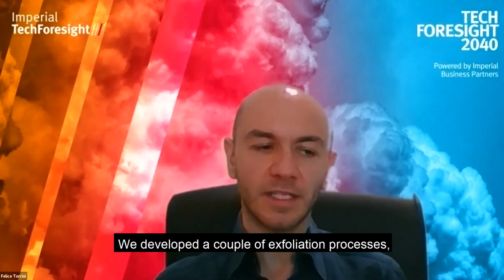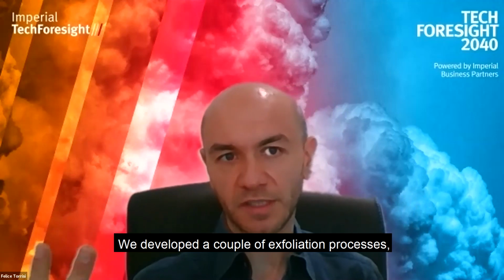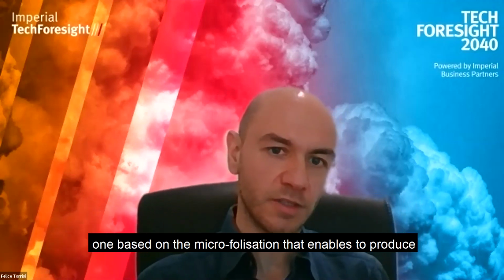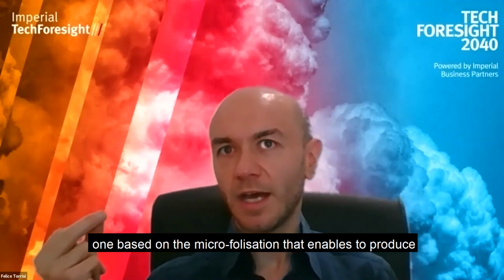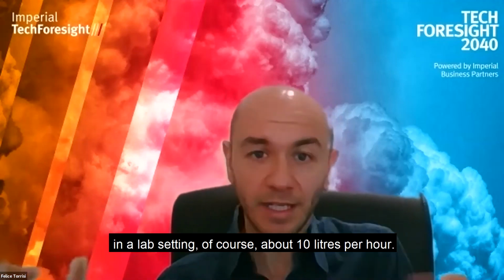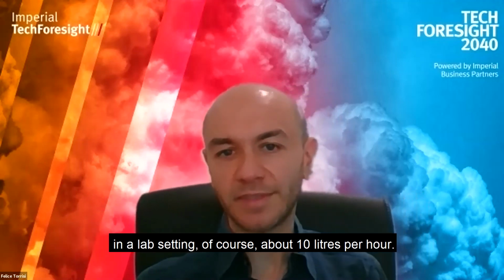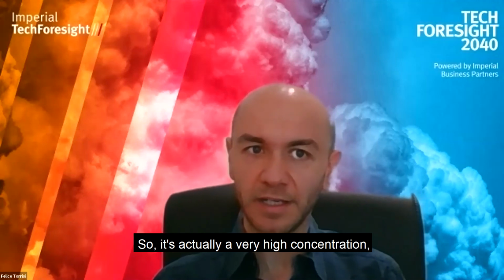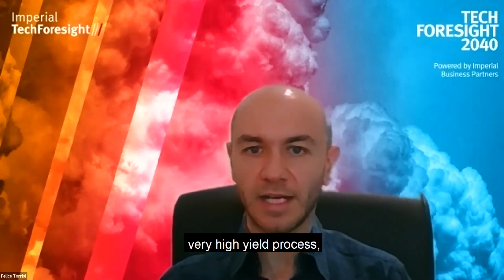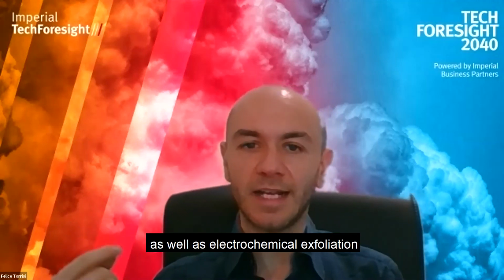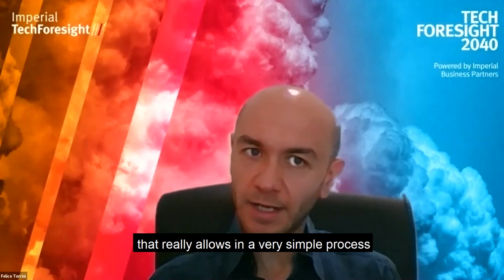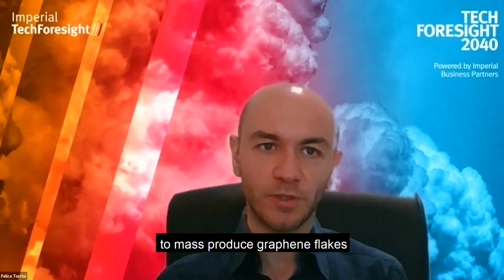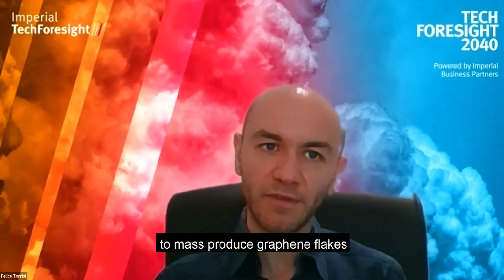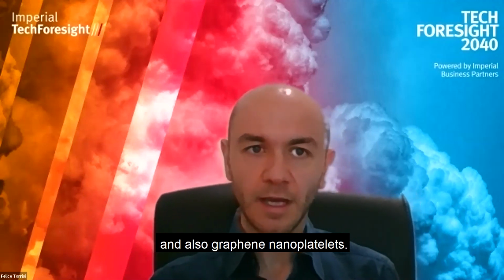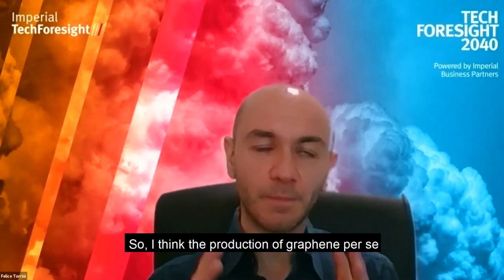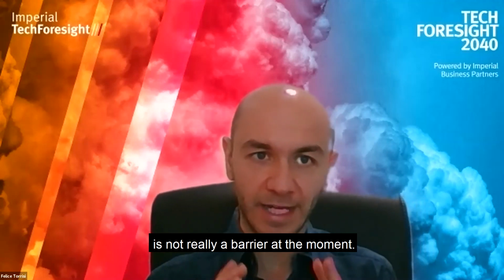But we developed a couple of exfoliation processes, one based on microfluidization that enables us to produce, as I said, around 10 liters per hour in a lab setting. So it's actually at a high concentration, a very high yield process, as well as electrochemical exfoliation that really allows, in a very simple process, to mass produce graphene flakes and also graphene nanoplatelets. So I think the production of graphene per se is not really a barrier at the moment.